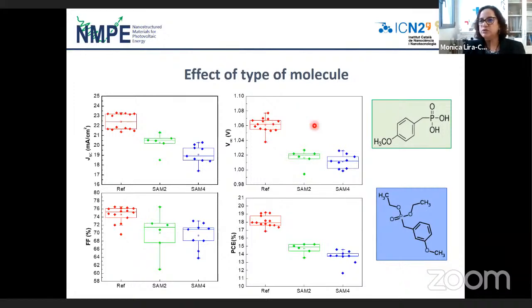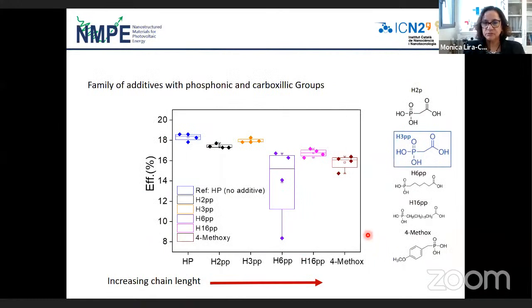So we were using a lot of these additives with two functional groups, and you will see it was very difficult to obtain even the same voltage or efficiency—the efficiency was always very low. So we finally arrived, after a lot of work, at this family of additives with the phosphonate and carboxylic groups.